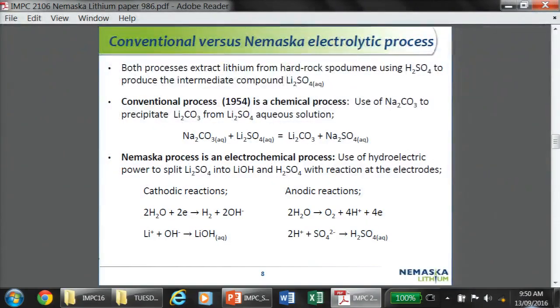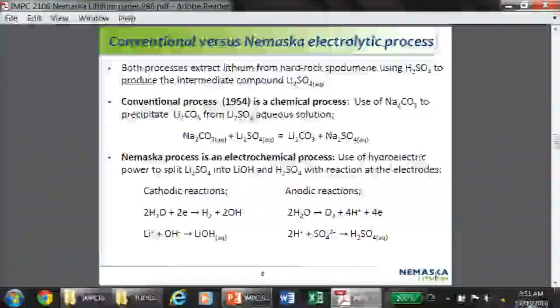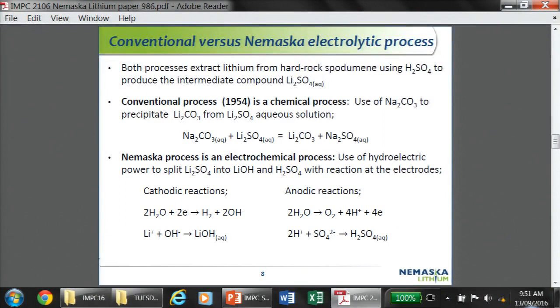But in this process, you create sodium sulfate, salt cake, as a byproduct. Salt cake is a dihydrate mud. At the time when this process was invented, it was not a problem. You threw the salt cake solution byproduct in the river nearby the plant. There was no problem. But today you cannot do that anymore. So today you have to crystallize the salt cake, you have to dry it, and if you want to reduce the cost of this dihydrate compound, then you remelt it in its own water of hydration and recrystallize it. So it's quite a significant chemical process, and salt cake sticks everywhere